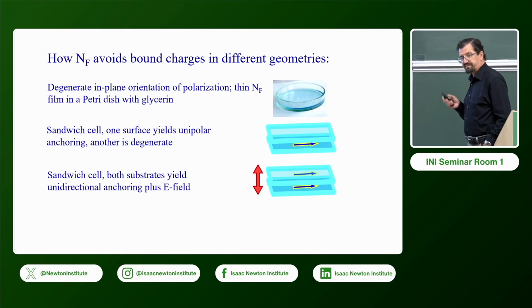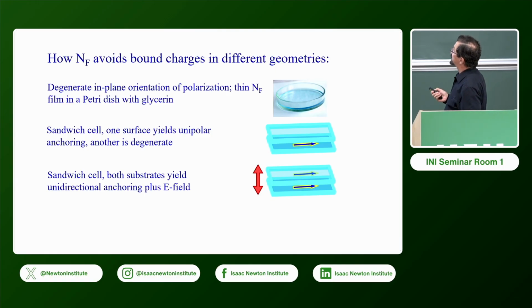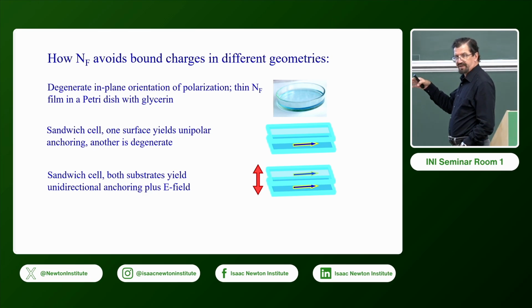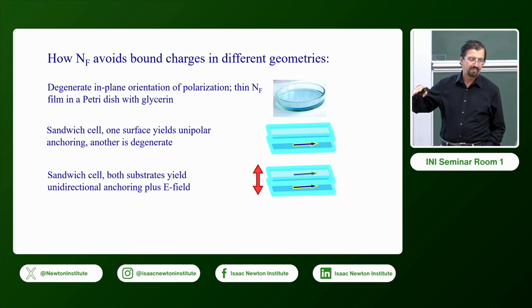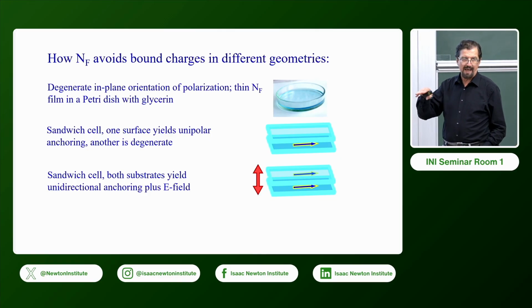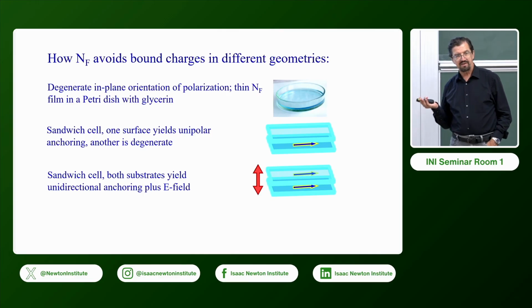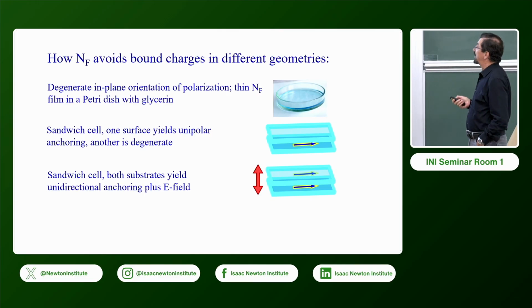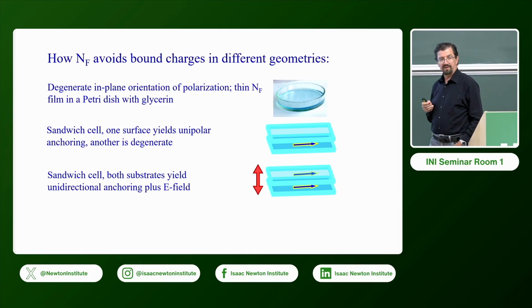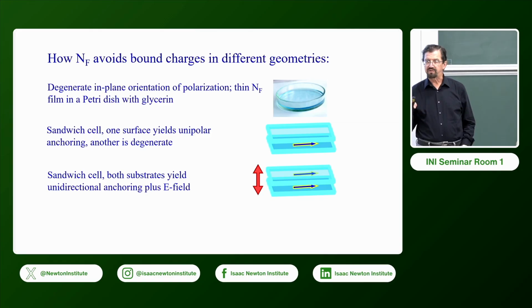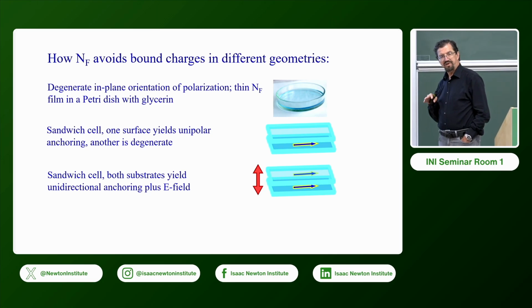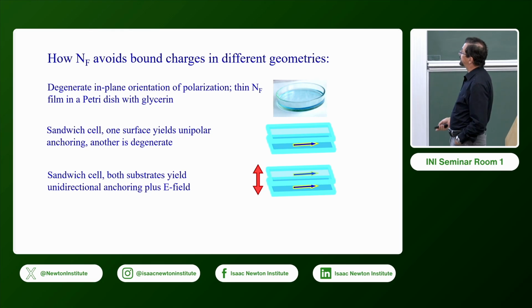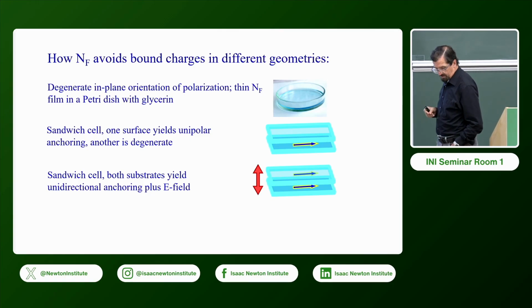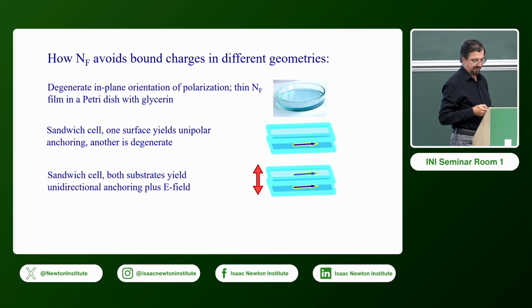And we decided to start with very simple experimental settings. In one case, we would deposit the thin film of a ferroelectric nematic on the isotropic fluid substrate. It's glycerine. There is no in-plane axis in such a setting, and the ferroelectric nematic can adopt whatever structure it wants. Then we will make the problem a little bit more difficult by placing the film of the ferroelectric nematic between two plates, and one plate is still azimuthally degenerate, but the second plate is treated to provide a single direction of orientation. And finally, the last part of the talk will be about a uniformly aligned ferroelectric nematic and the electric field that is applied perpendicularly to the slab.